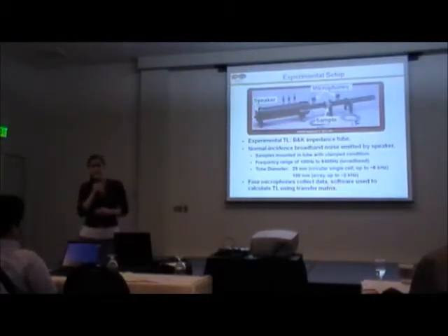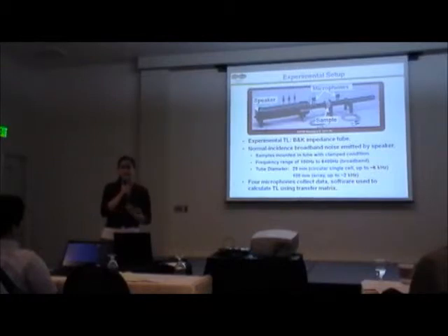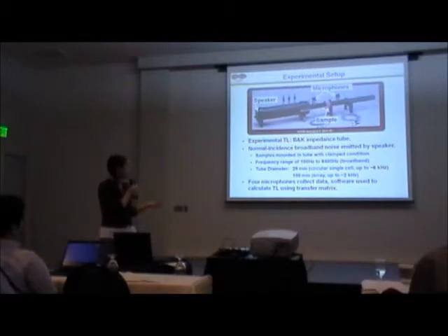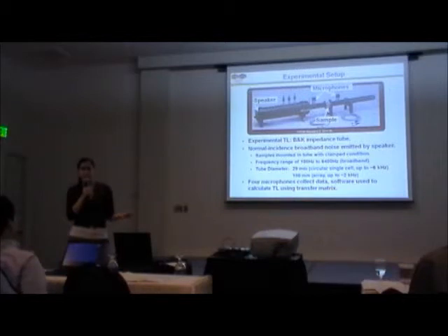The experimental setup to measure transmission loss is called an impedance tube. The sample is mounted here and excited by a speaker. The speaker emits plane wave sound waves at a variety of frequencies or as broadband sound, and then microphones,